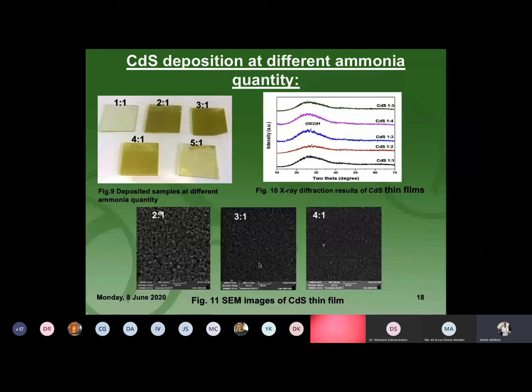At 2:1 and 3:1, the deposition of films increases, and after 3:1, as you can see from figure 9, the deposition of the film is decreasing, and even at 5:1 it is completely gone. That means the ammonia at 5:1 is controlling the cadmium ions completely, so there are no reactions occurring.